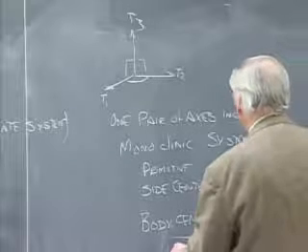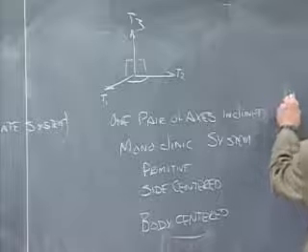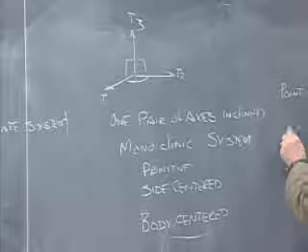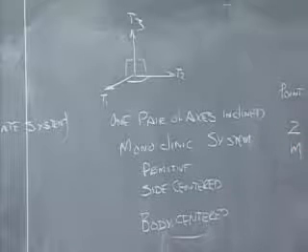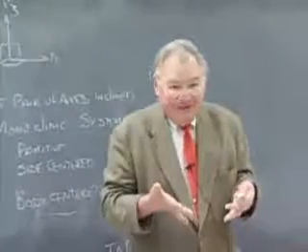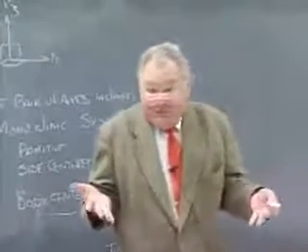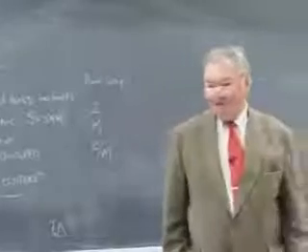These lattices were compatible with point group 2 or point group M. We obtained a lattice of the same shape with point group M or with point group 2. And if it works for 2 and it works for M, why not both at the same time? It would also work for 2 over M. Twofold axis perpendicular to a mirror plane.